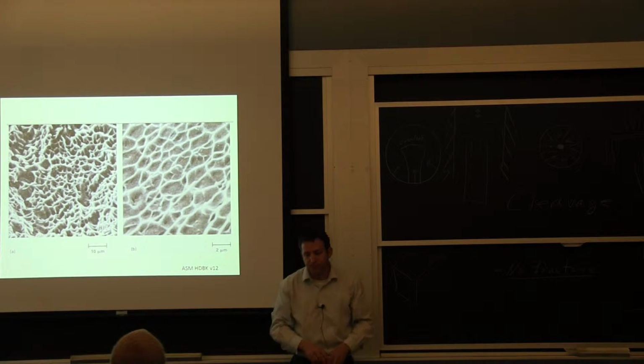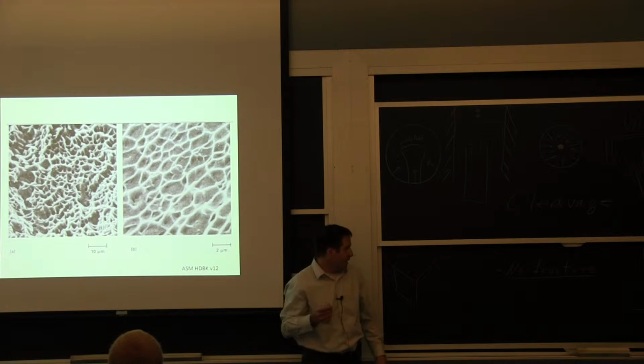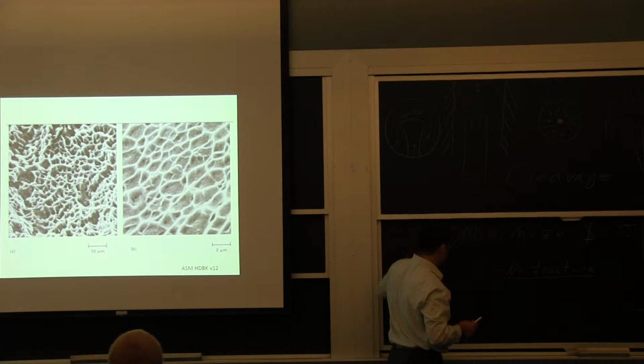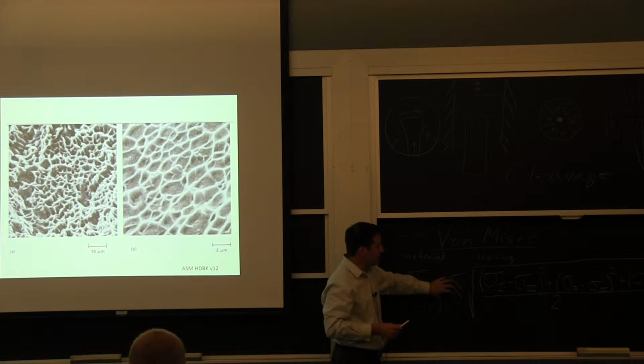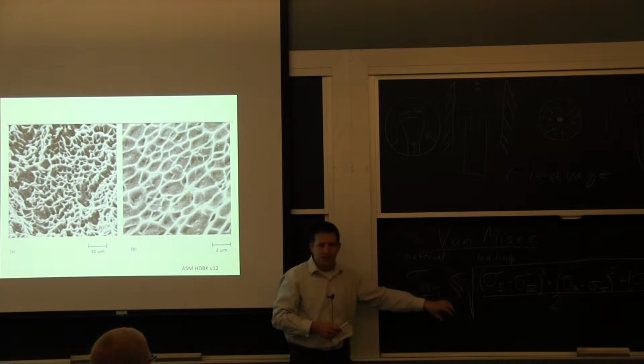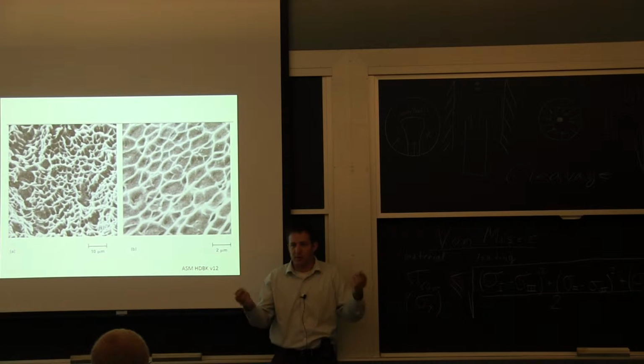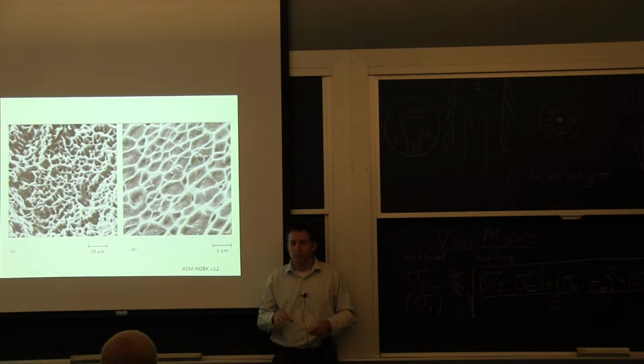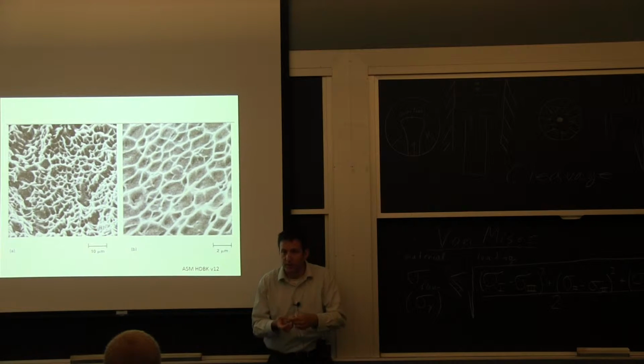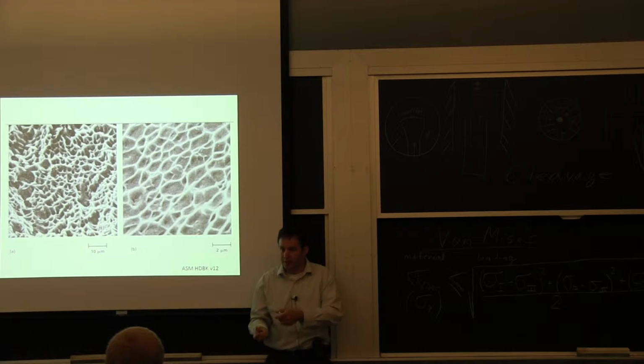Okay, high temperature. We are forming voids, and it's not something that comes straight out of this equation. If it was just for von Mises, we would keep deforming and deforming and deforming. Eventually, you have small particles, inclusions, or grain boundaries. There are a lot of pieces in the microstructure where you're going to start forming small voids. And depending on the quality and the purity of your metal, these voids will form earlier or later. If you have more stresses, if you're looking at a high strength material, they will form earlier because your stress is higher when you start deforming.